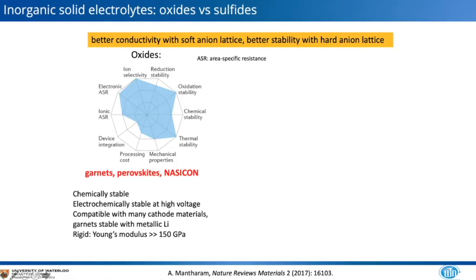So examples of oxides include garnets, perovskites, NASICON-type materials. These are all relatively chemically stable, electrochemically stable at a high voltage. They're compatible, as I said, garnets with metallic lithium, but they do have this unfortunate rigidity, the very high Young's modulus in the order of more than 150 gigapascals. And that makes them non-conformable and rather difficult to process into cells.